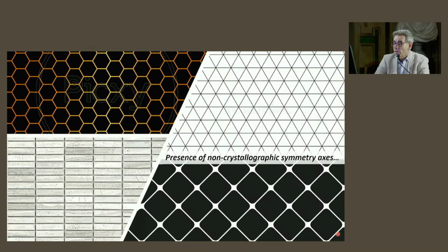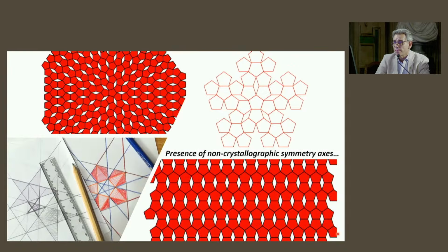And indeed, if you look at 2, 3, 4, and 6-fold symmetry axis, covering a 2-dimensional floor, what about 5? If you try to cover a 2-dimensional plane with pentagons, governed by 5-fold symmetry axis, you are immediately stuck, because pentagons cannot cover a 2-dimensional plane without leaving gaps and cracks among the tiles. So pentagons are governed by 5-fold symmetry axis, which is a non-crystallographic symmetry axis. But unfortunately, this is what occurs in a 2-dimensional plane.